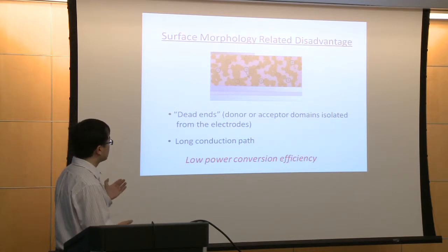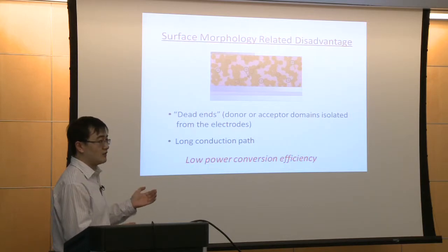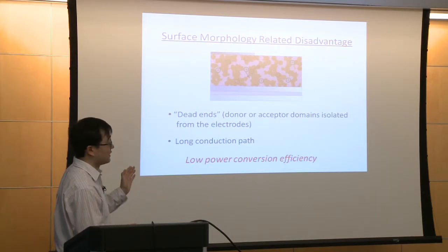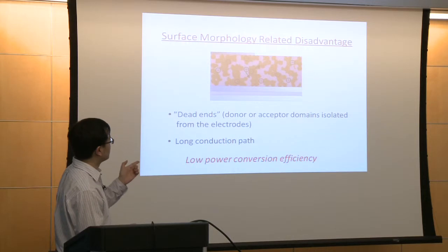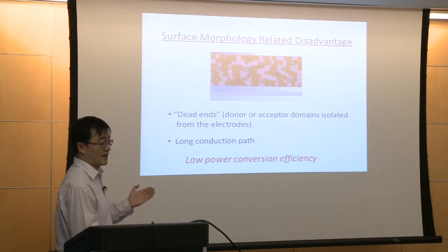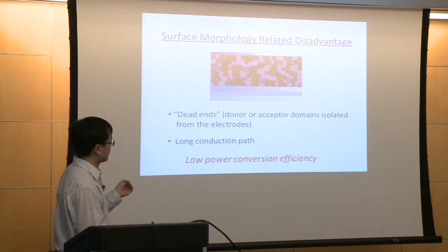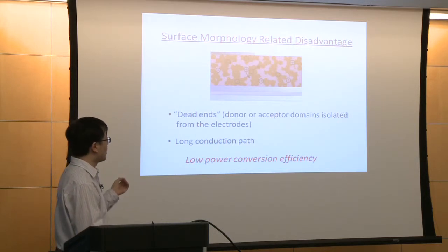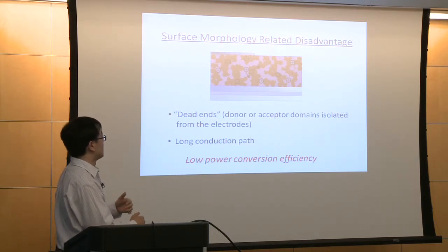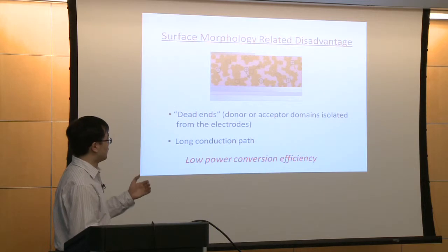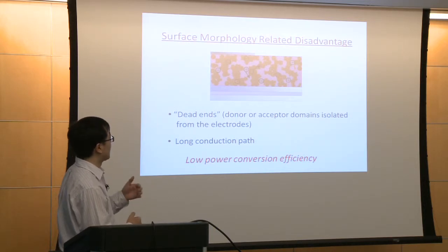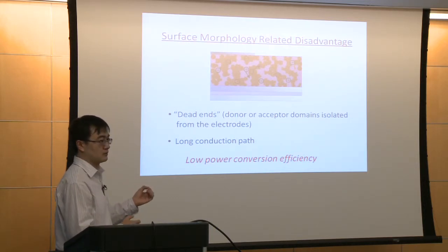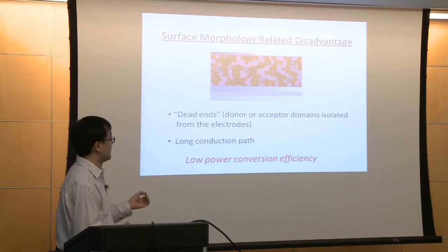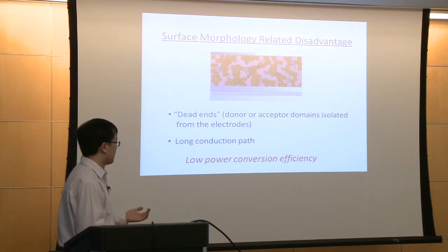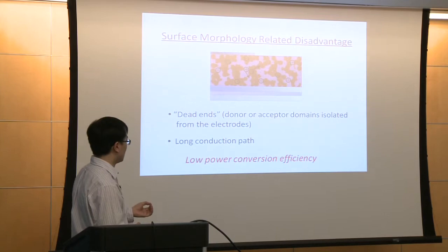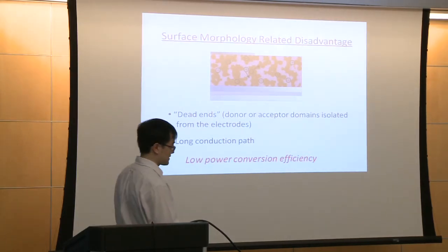And also, even if it finally finds some way to get to the electrode, you can imagine there's a very long conduction pathway, for the electron or for the hole. So this will cause very high resistance for the electrons or for the holes trying to get to the electrode. And this phenomenon will significantly lower the power conversion efficiency.